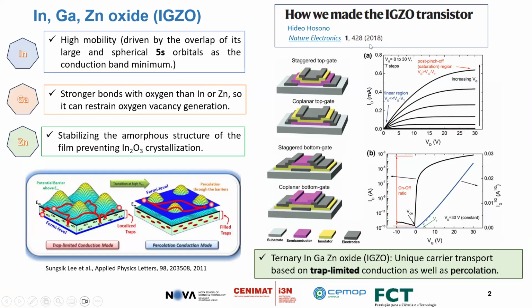It is from 2018, and it was written by Hosono about this IGZO transistor, which is very nice historically and also scientifically explained in this article. Briefly talking about the material, for example, the presence of indium, due to having these large 5s orbitals, gives high mobility because of the overlap of these large orbitals. So there is no restriction, and they can have very good mobility, giving this property to the material.